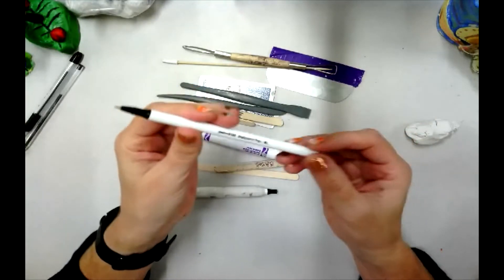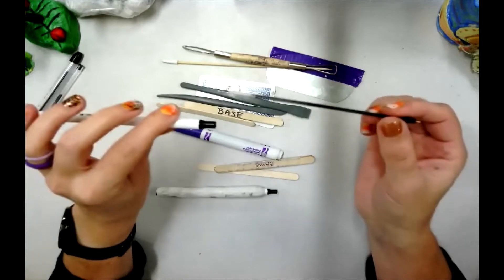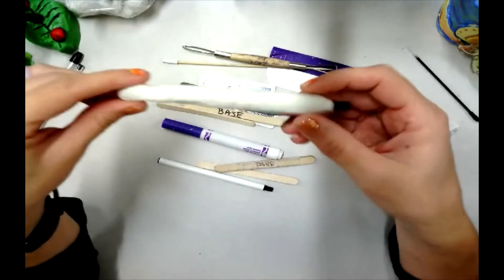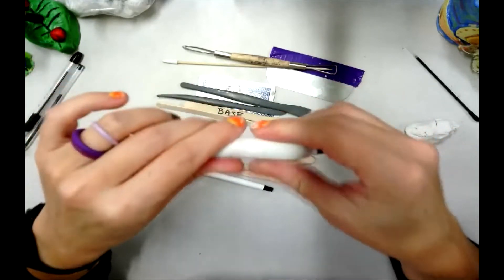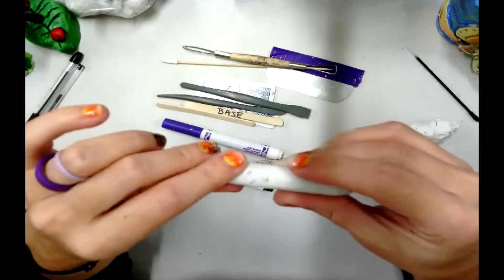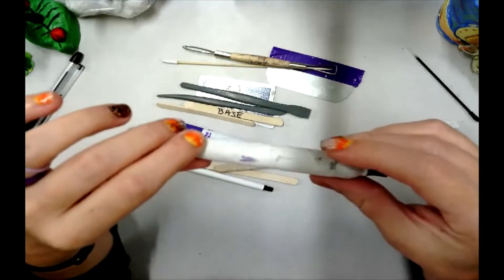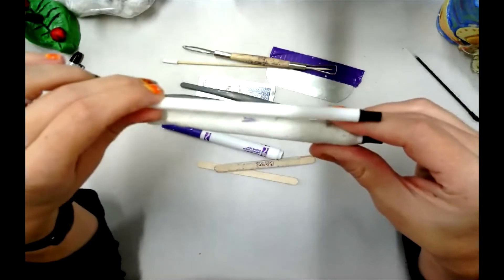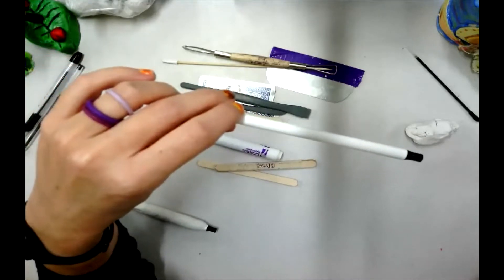I just bought packs of these at the Dollar Tree and they work just fine. What I did before I gave them to the students was I removed the ink inside because you cannot bake it with the ink inside. The first step is that you have to coat your pen with polymer. You have to bake the polymer at 275, 15 minutes per quarter of an inch.